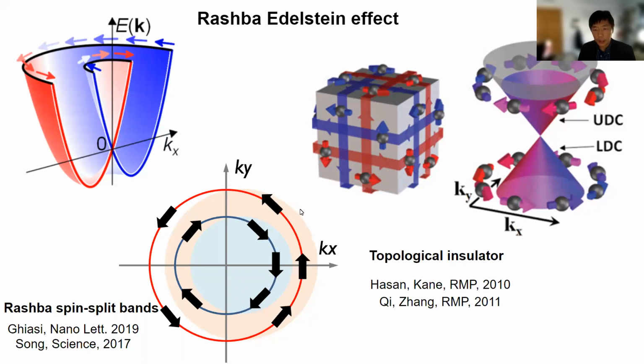This type of spin texture is also commonly seen in, for example, topological insulators, particularly in the surface states of those materials. The surface states of the topological insulator have a linear dispersion relation, which can be described by this Dirac cone, and the electron and the spin also have this well-defined spin-momentum locking. One point we can make is that the spin polarization that arises from the Rashba-Edelstein effect is what we call a Fermi surface effect, because it comes from the shift of the Fermi surface. Whereas the Spin Hall effect we view as coming from the Fermi sea, because it is a phenomenon that comes from the collective contribution of all the electrons deep in the Fermi sea.